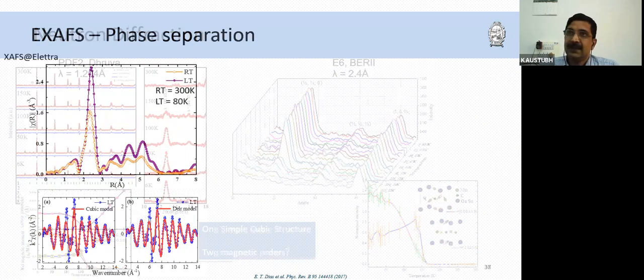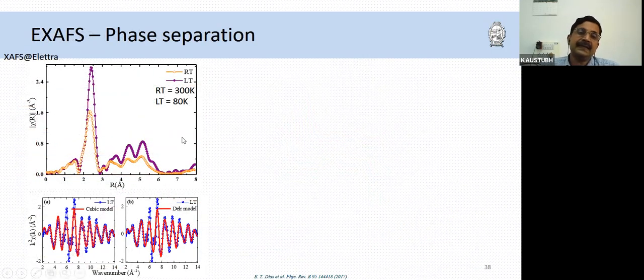Now we did EXAFS, and these experiments were done at Elettra, at room temperature and at liquid nitrogen temperature, and we tried to fit the data with the known structure, that is the cubic model, and there were some discrepancies. This is the K-space data, so I'm showing you raw EXAFS, and we could not fit it, neither with the cubic model, which is using the constraints of the structure, nor with the relaxed model, so the distortions and things like that.